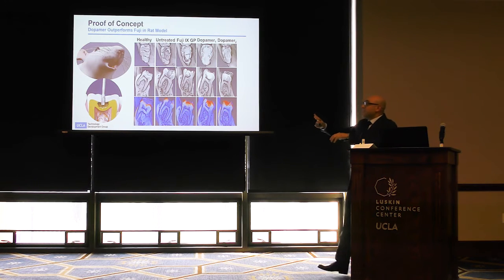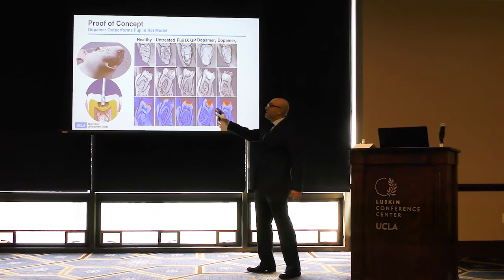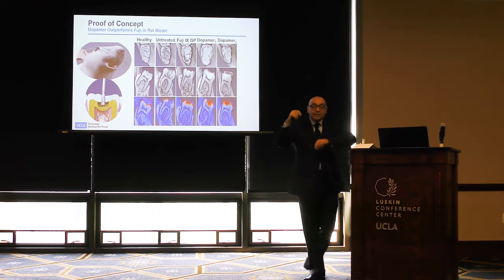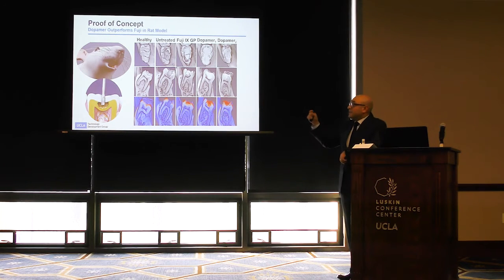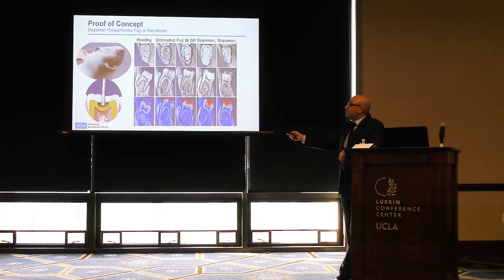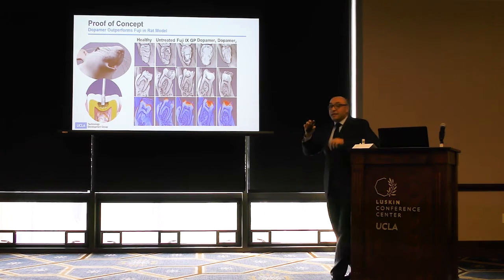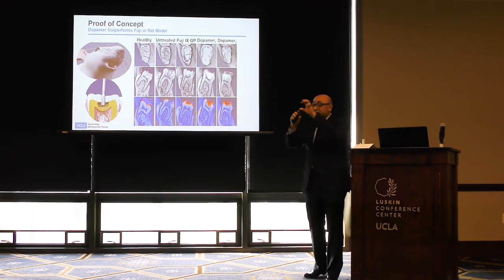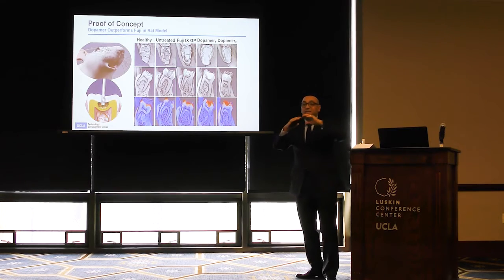So what we did next is we used rats as an experimental model, and we placed a small filling in the teeth of the rat, and we made a small exposure here. So the pulp was exposed, and we used 2 different concentrations and 2 different formulations of dopamine filling material. You can completely appreciate here that whenever we have dopamine filling material, it induces dental pulp stem cells inside the nerve of the tooth to regenerate dentin.